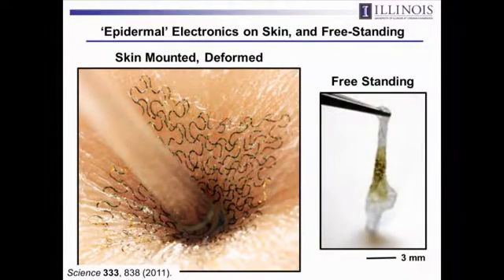So here's what it looks like when it's mounted up onto the skin. Very soft, no penetrating pins, no adhesive, you just laminate it on. Good to go. Same kind of experiment. This is laminated on the skin of the postdoc who did the work, and then we poked them with a glass rod so you can kind of see how that moves around. If you grab it at an edge, you can peel it off. This is what it looks like. It's so flexible and floppy and soft, it doesn't even support its own weight. It just kind of collapses down onto itself, to give you a sense of the mechanics.